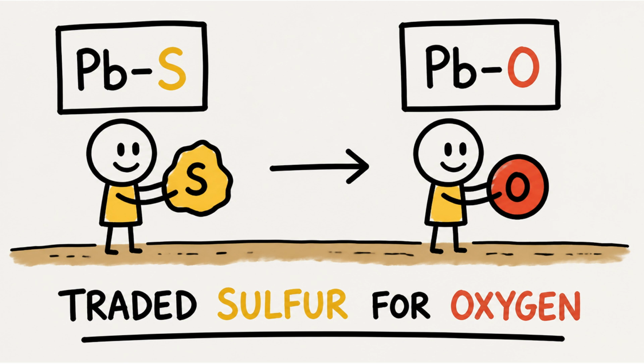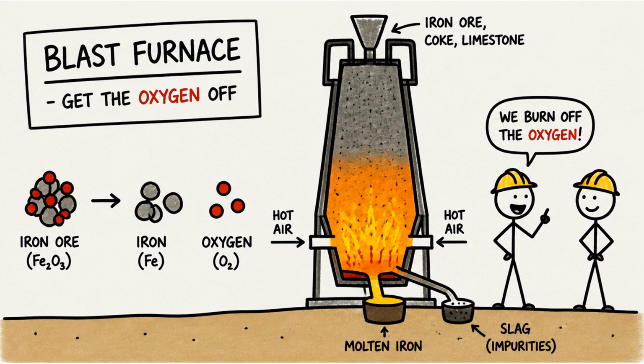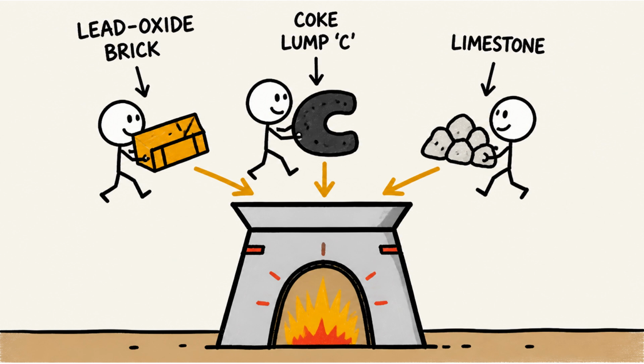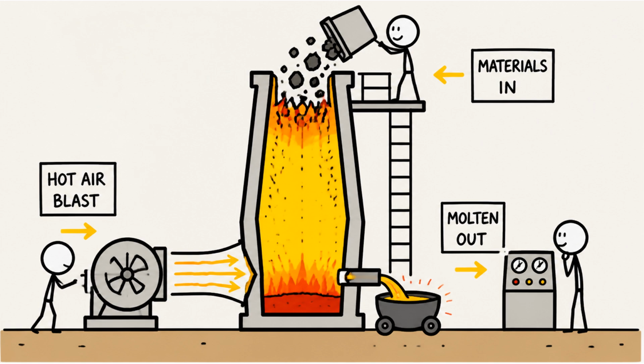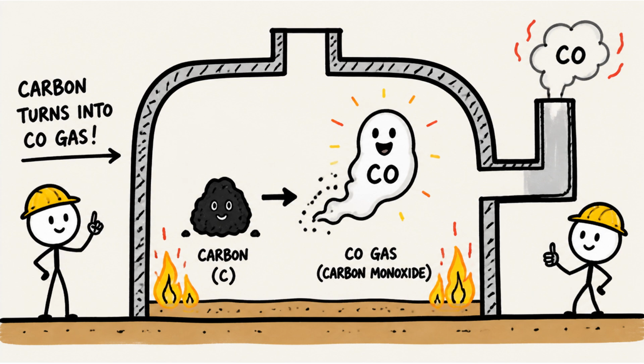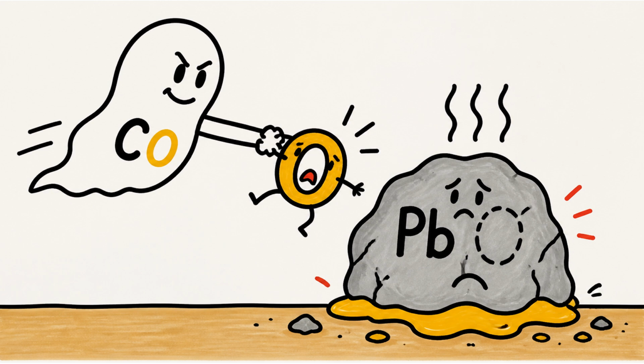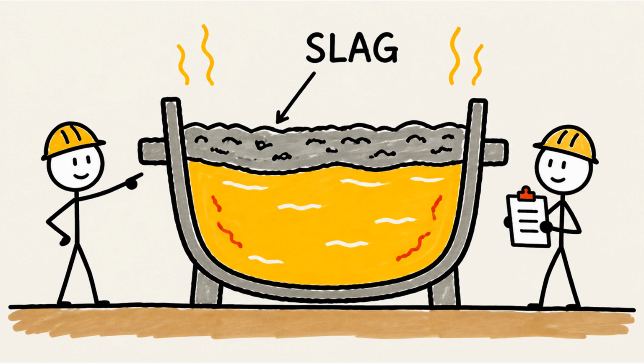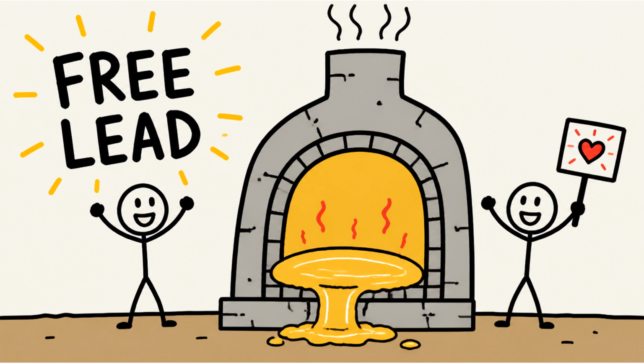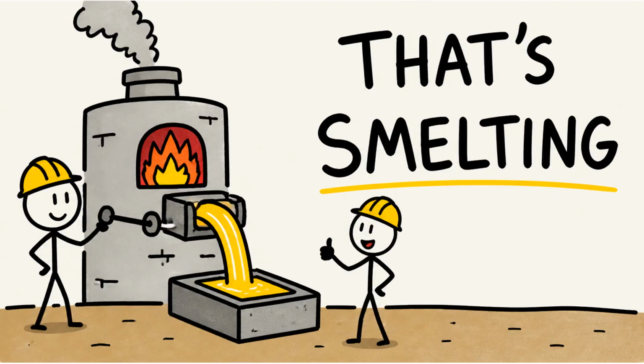The lead has traded its sulfur for oxygen, and that's a problem we can actually solve because now we just have to get the oxygen off. That's the job of the blast furnace. The roasted material, mixed with coke, which is almost pure carbon, and limestone is dumped into a towering furnace and blasted with hot air. The carbon, starved of oxygen, becomes a hungry gas called carbon monoxide, and that gas tears the oxygen right off the lead. The rock melts. The waste floats up as a glassy slag, and the lead, heavy, molten, finally free, sinks to the very bottom and pools there, and is tapped off like water from a barrel. That is smelting. That is the whole job of it.